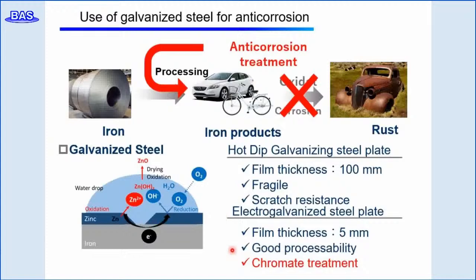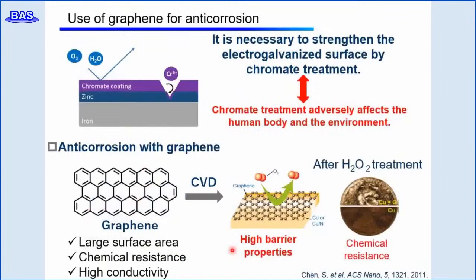However, since it is difficult to increase the thickness of the galvanized layers, chromate treatment is generally applied. While chromate coating has excellent barrier properties and self-healing capabilities, the hexavalent chromium in the film has a negative impact on the environment, and regulations are being tightened. Therefore, new corrosion preventing methods are being actively studied as an alternative to chromate treatment.